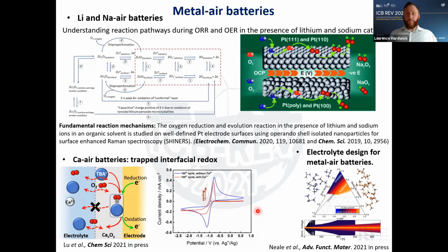So this just highlights some of the recent work we've been doing within the field of metal oxygen batteries. We've been using single crystals to really unpick and understand some of these reactions taking place within the oxygen reduction and oxygen evolution reaction in the presence of lithium. We've used very well-defined electrodes, single crystals, to compare different reactions of sodium and oxygen on different surfaces, and we've observed using SHINERS different reaction pathways. On some specific surfaces, we just see a sodium superoxide species. Some surfaces also promote the formation of a molecular sodium peroxide on the surface. And so we've identified this surface effect on driving different reaction mechanisms.